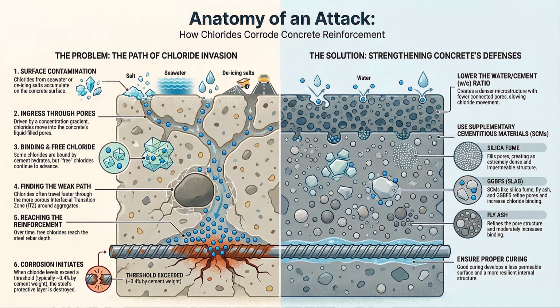It is a significant practical trade-off, you're right. Silica fume increases the viscosity and the stickiness of the fresh concrete. It often demands more specialized admixtures and extremely precise on-site handling, which is a huge logistical challenge in 50-degree heat. But the performance gain is worth it. It's irreplaceable. SF mixes achieve the lowest overall diffusion values, sometimes dipping down to 0.2 to 1.2 times 10 to the minus 12, and that's why blending is so key. You pair GGBFS's superior chemical binding, trapping the chlorides, with silica fume's superior physical barrier slowing their arrival, to create this dual-layered maximum security structure.